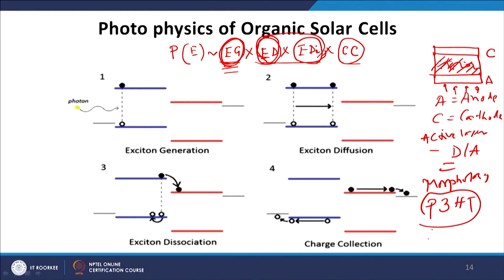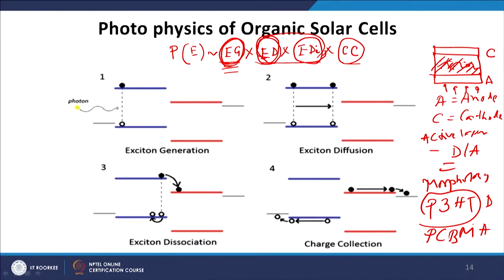So, here we are using P3HT:PCBM, for example, to make the material. One is the donor, another is the acceptor. So, the first thing is it depends upon which solvent we are using to make the films. Second thing is it depends upon the ratio of the donor to acceptor, and it has been observed this ratio matters a lot. If I use a 1 to 1 weight ratio or if I use a 1 to 4 weight ratio, the morphology is way different. Similarly, once we mix this donor and acceptor materials and spin coat it on a substrate, we will get a film.